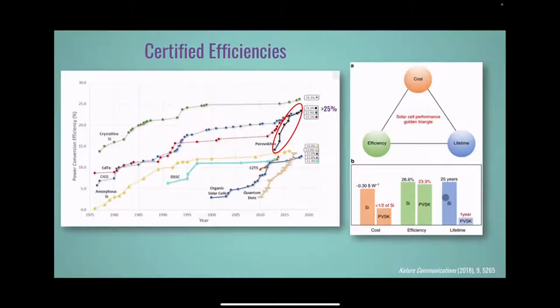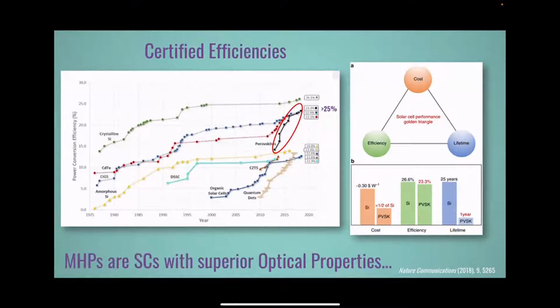Of course, the real problem of these solar cells containing metal halide perovskites is the lifetime, because they are very moisture sensitive, and also they tend to degrade under continuous illumination. Anyway, they are extremely interesting, and we may expect in the next 5 years to see these perovskite solar cells on the market, also because they can be printed, so you can prepare flexible solar cells, which cannot be done with silicon.